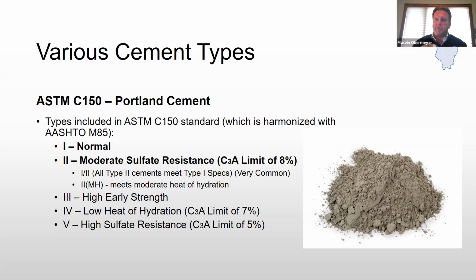But when the Blaine is higher, there's more surface area. When there's more surface area, it will achieve higher, earlier strengths. It also will set up faster. Usually used for precasters and pre-stressors or winter applications. Works very well. And actually that product sometimes has a little bit more gypsum in it. I'm splitting hairs. Type 4 is low heat, limit of 7% on the C3A.